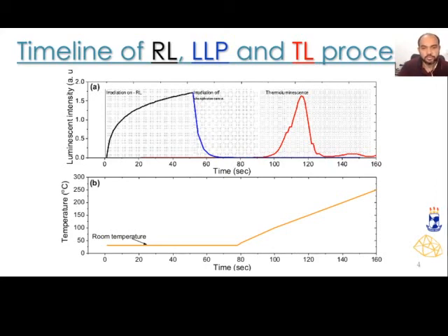When the irradiation is turned off, the luminescence does not decay abruptly. It decays slowly, and we can say that this is the phosphorescent emission. This is because of the trapping of charge at shallow traps. Both processes can occur at room temperature. When the sample is heated at a constant heating rate, we can get the thermally stimulated luminescence. That is the release and recombination of charge located at deep traps, on the other hand, charge located at stable levels at room temperature.